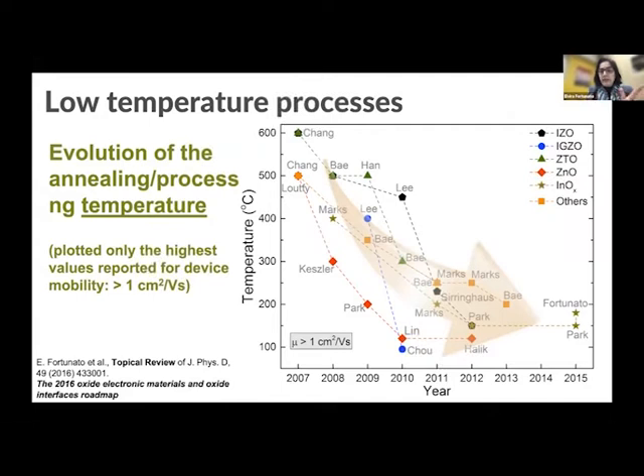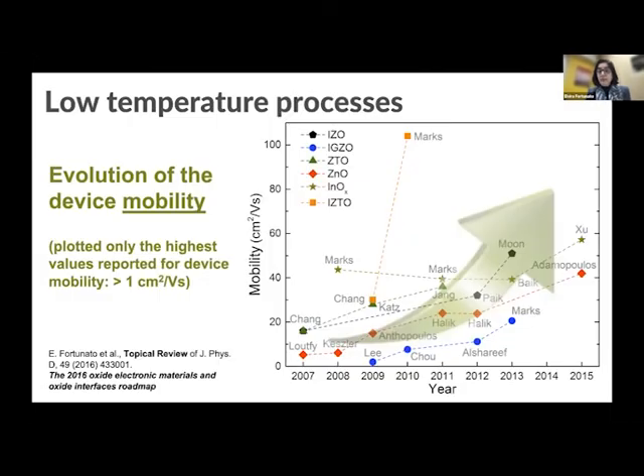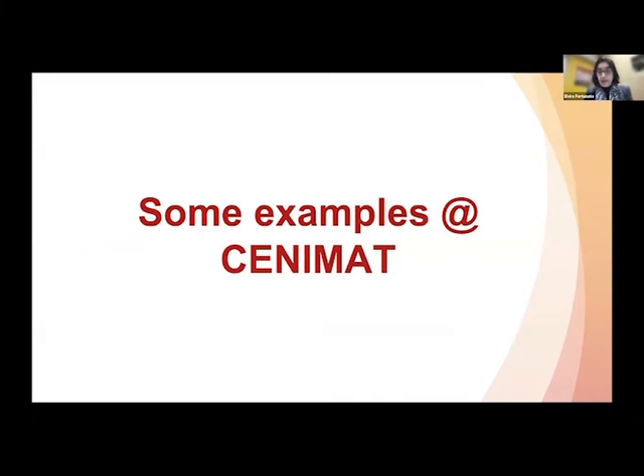Concerning the low temperature processes, in these graphics I present you just an overview about thin film transistors produced by a solution process, not using physical processes like sputtering or physical evaporation. What we observed over the years is that the first devices using just a solution process needed a very high final deposition temperature, but over the years we are now able to produce these metal oxide semiconductors using very low processing temperatures. And simultaneously, if we analyze the same devices in terms of mobility, as I mentioned, mobility is like a figure of merit, we observed over the years an increase in the electrical performance. So we are optimizing a lot all the chemistry associated with the precursors we are using, and we are not only using temperature, but also other sources of energy, like, for example, radiation.